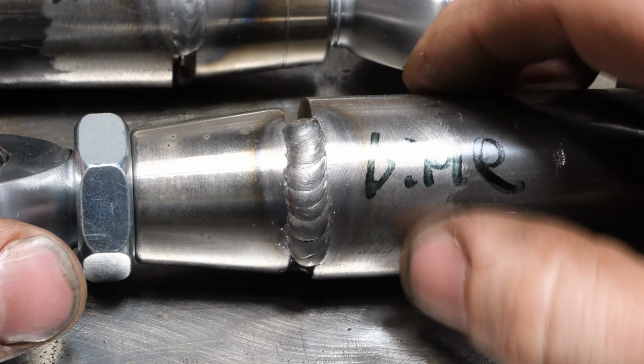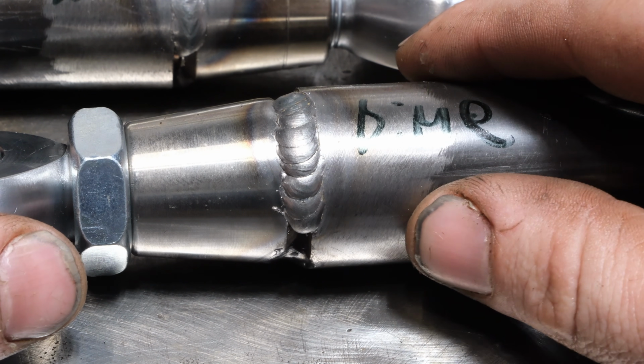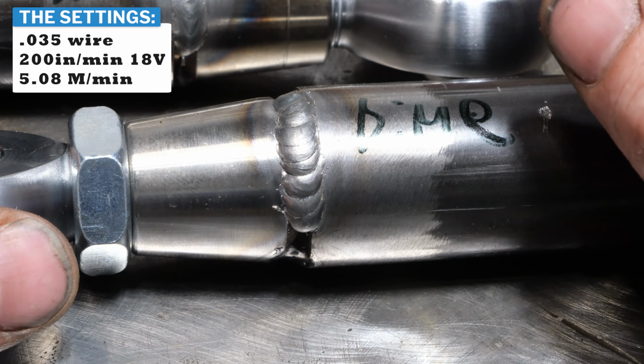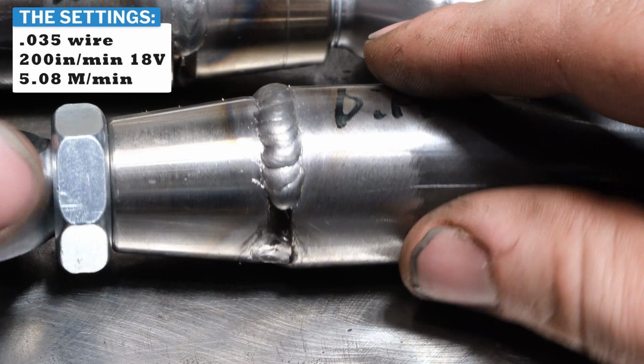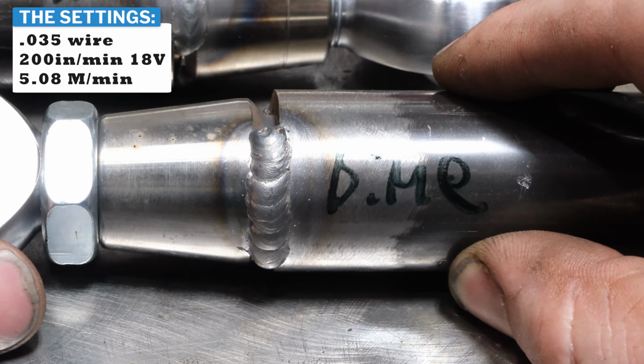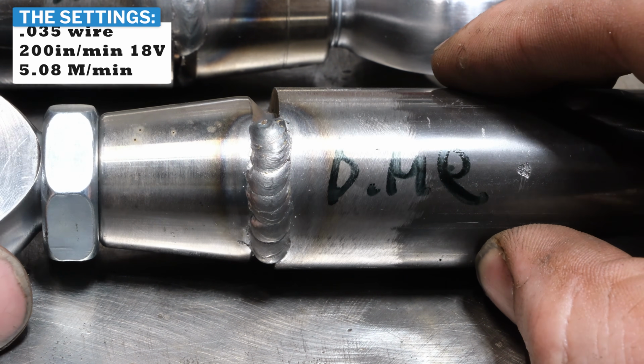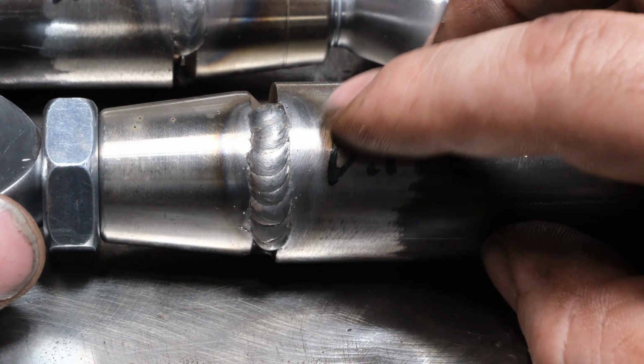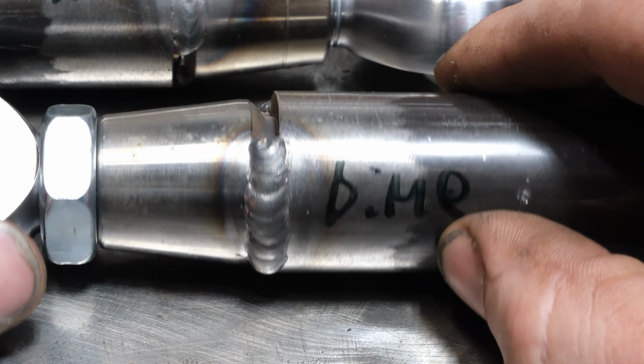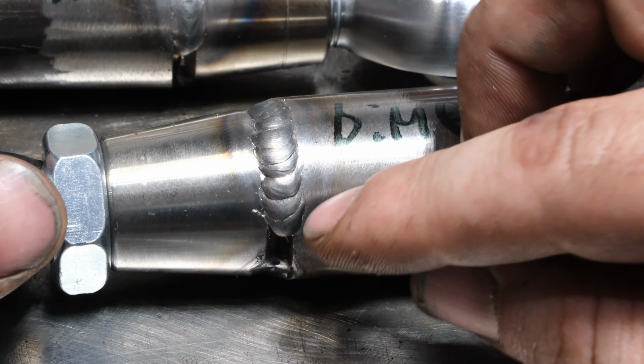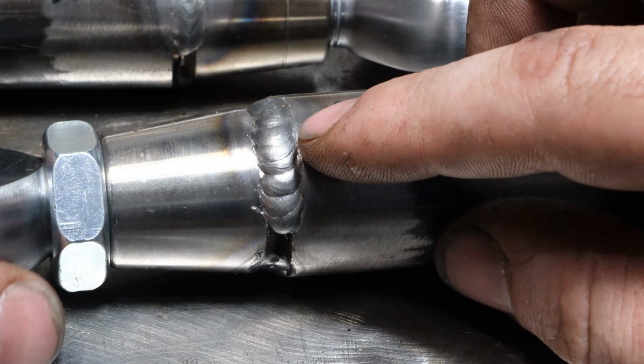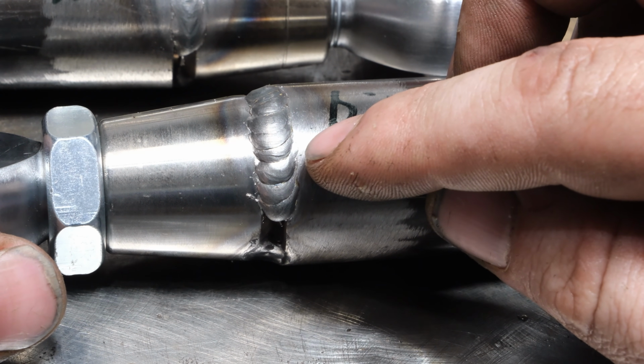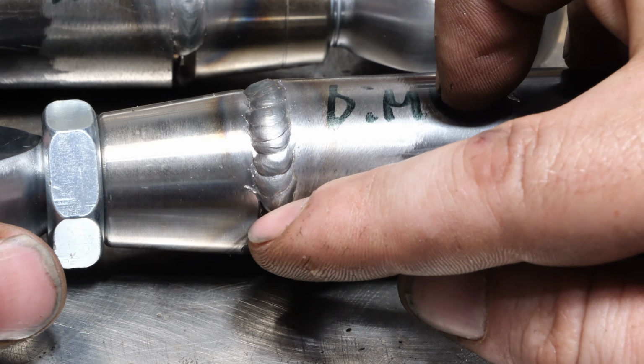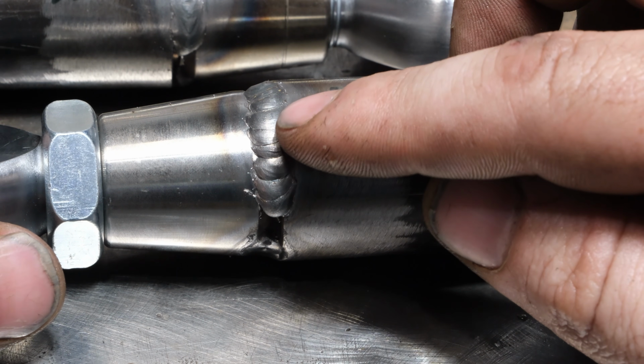Now let's look at the last weld I did. Now this is going to be somewhat controversial. I used settings that I used in another video to stack dimes. These dimes don't look that good, but it's the exact same settings, and with a little bit more practice, I could have stacked basically a perfect stack of dimes on these, which for a single pass is something you don't want to do, because when you run reduced settings on thick steel like this, you're going to end up with a severe lack of fusion.